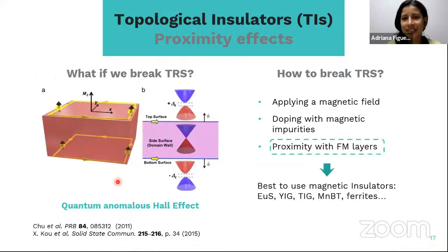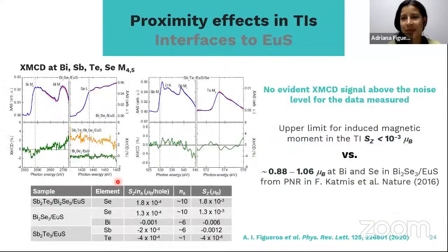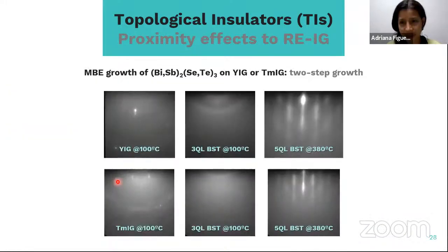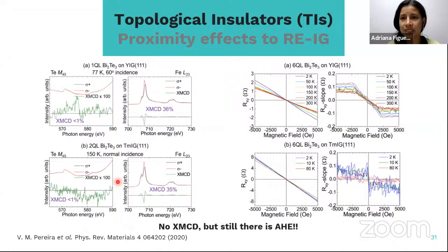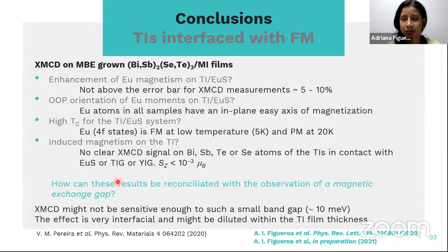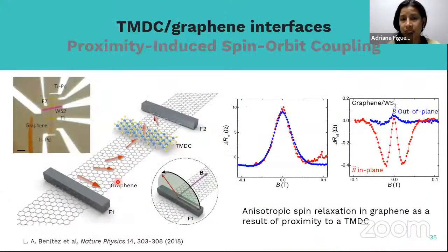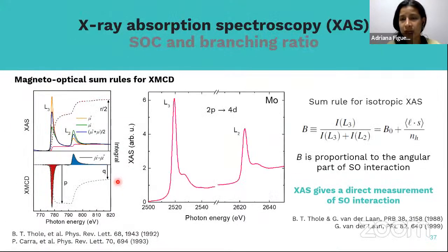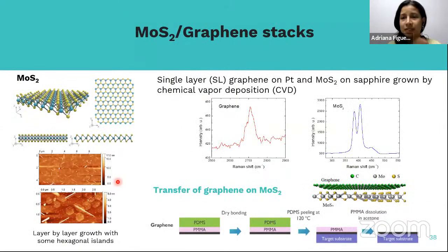I haven't tried. I mean, for these stacks that I showed, we haven't done it. At the beginning we had some samples that we wanted to try, but since we got these good materials with CVD, they had very good quality, so at the end we took these samples. We didn't try with exfoliation and transfer from crystals. And also here with CVD, what you manage is to have a large covering area of both graphene and MoS2, and this is what we want for this kind of measurements, because that way we gain in signal.